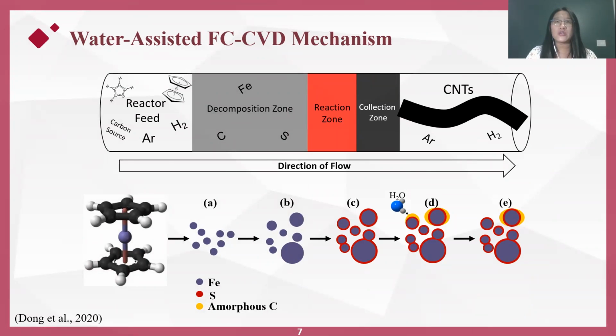Although still somewhat controversial, one of the most widely accepted mechanisms begins with the iron-containing precursor, ferrocene, decomposing at high temperature to release iron atoms, which form nanoparticles of different sizes after interparticle collisions and agglomerations. Similarly, the sulfur atoms shown in red here were released from the thermal decomposition of thiophene. It bonds and coats the iron nanoparticles on the surface, which inhibits further catalyst particle growth. Until now, at stage C, we have a typical active catalyst particle for CNT growth.